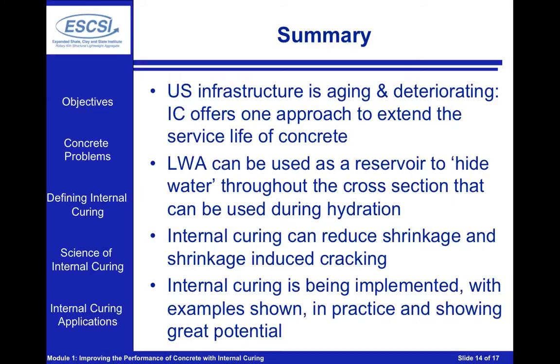Finally, what we've seen is there are several different groups that have been using internal curing on a full-scale basis. This internal curing is as simple as replacing a portion of the sand in our system with fine lightweight aggregate that's been pre-wetted. These examples have been shown, and in practice, this is showing great potential. The one thing we do need to be aware of is we do need to do quality control testing on our lightweight aggregate to make sure that we understand our moisture content. But once we've done that, and once we've done our proper adjustments for our moisture content, this really looks and places like a conventional concrete.